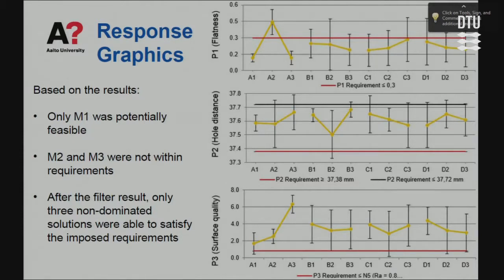So then also looking at the surface quality, you realize that, okay, requirements are here, and none of the average values is able to fulfill the requirement. But if you see the standard deviation, in certain combinations you fulfill the requirements. So you can see also from the sensitivity side that the surface quality is the most difficult to fulfill. I mean, that's obvious. It's what everybody knows about 3D printing. Surface quality is bad. And you can extract more conclusions from here, but I'm not going to go into that.